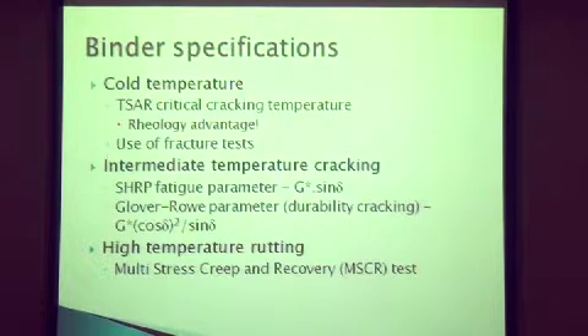In the intermediate temperature, we have this SHRP fatigue parameter, which was developed based upon dissipated strain energy. G star times sine delta is related to the dissipated strain energy. And this is what I did my PhD work on.